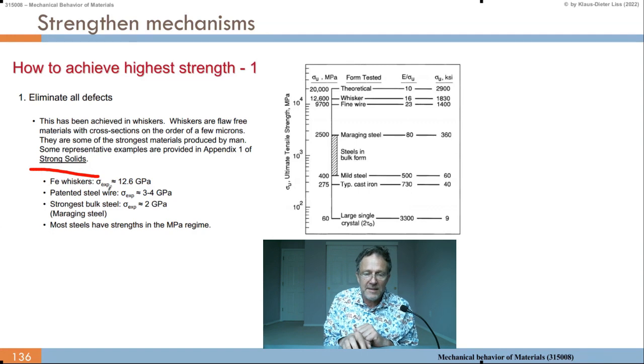There are iron whiskers, for example, where the experimental sigma is 12.6 gigapascal. There's a patented steel wire where we have 3 to 4 gigapascal strength. Then the strongest bulk material, steel, is about 2 gigapascal. And most of the conventional steels have strengths in the megapascal regime. That is also shown here in the table to the right.